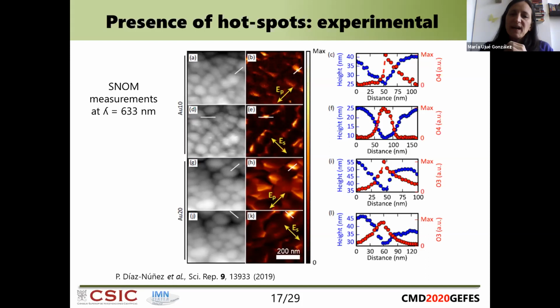Well, because we have the solid layer, the gold there, usually what you do is you decide a height, and then you stay all the time at the same height to not have too many artifacts. And usually you need to measure 10, 20 nanometers from the surface, because if not, you risk crashing your tip and everything. So you are not really trying to go inside, or at least not too much.